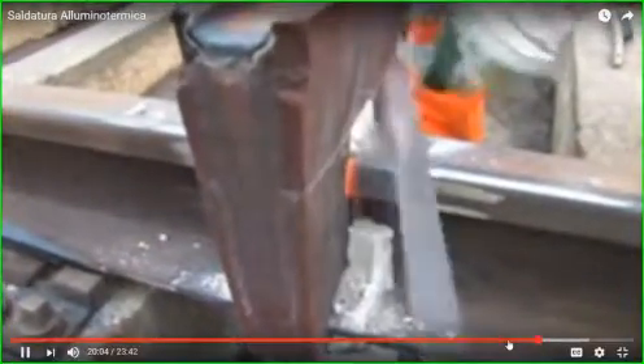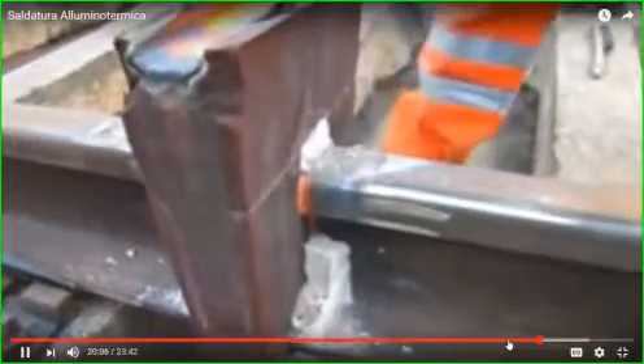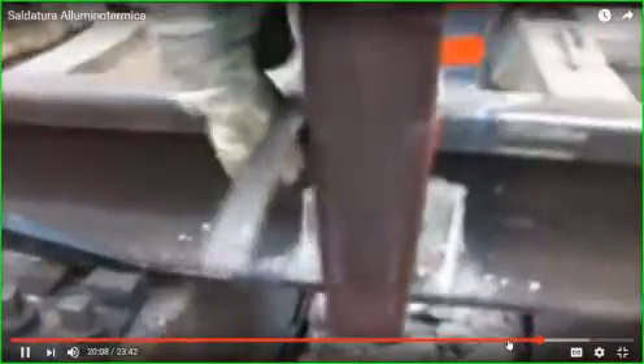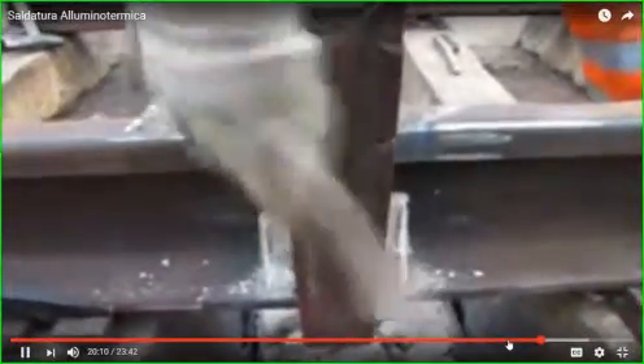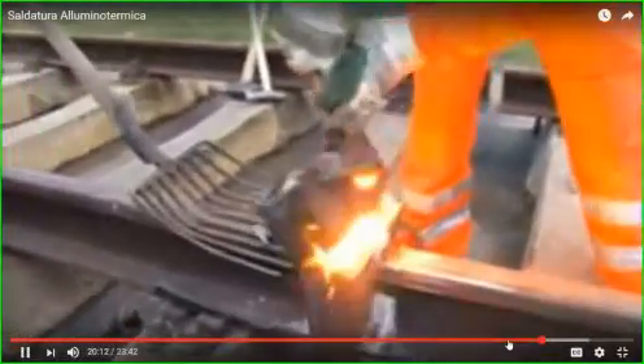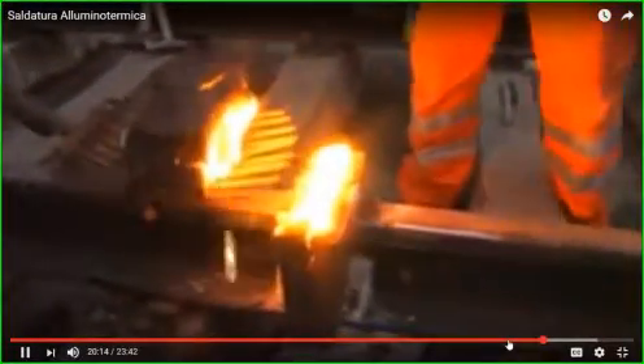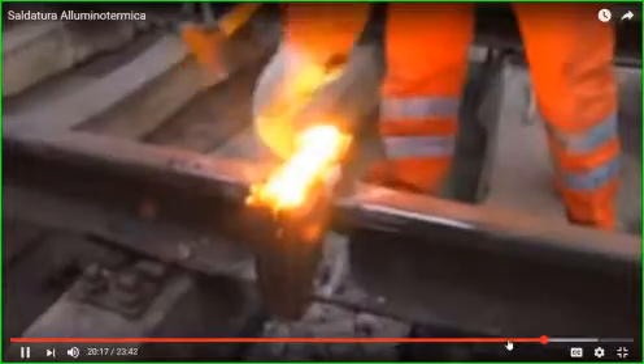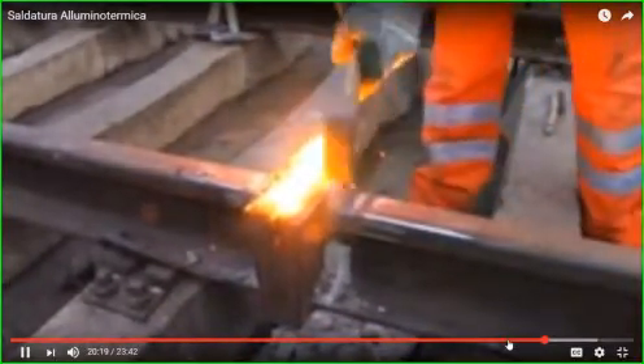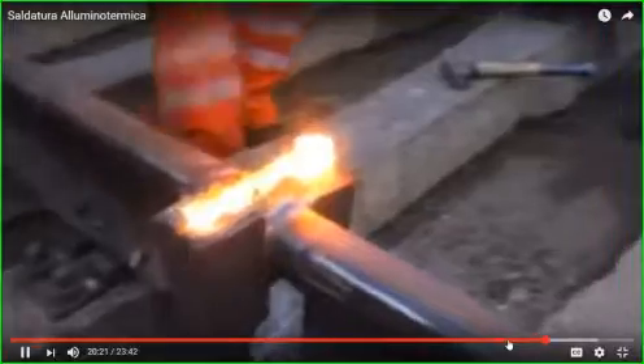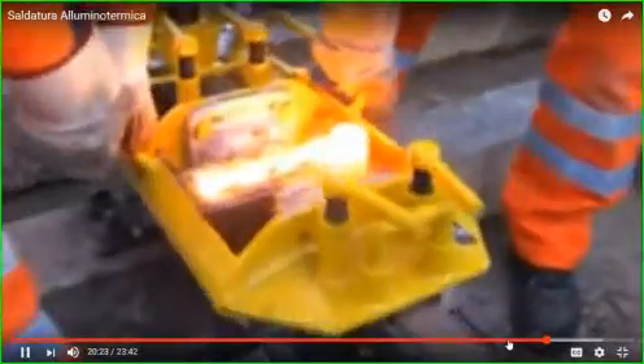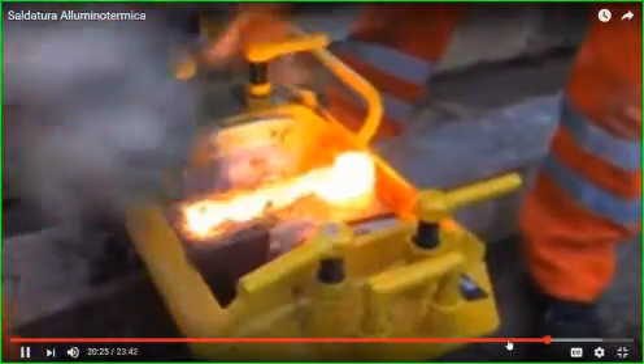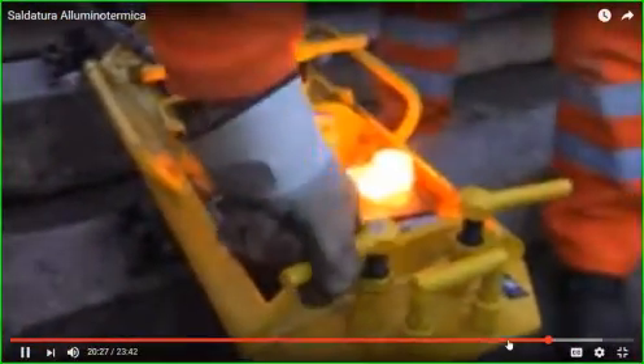Predetermined breaking points on the molds are to be created. After another waiting time after pouring, the mold head including the slag is put off. The running surface is to be cleaned of all residues. A hydraulic trimmer is used to cut the excess metal from the weld. The cutting height over the running surface is limited due to the down holders.